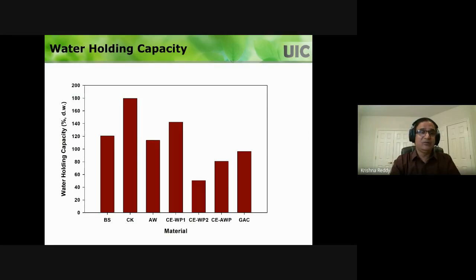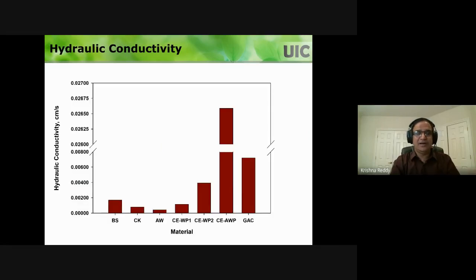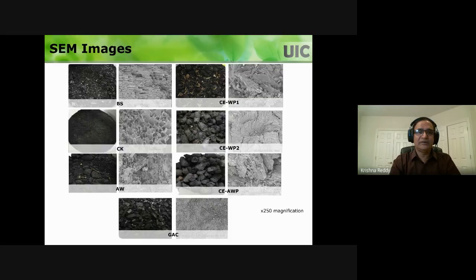Here, for water holding capacity, one of them has 180%, the other one has hardly 50%. For hydraulic conductivity, they are generally more like granular material, so they will have high permeability. No matter which biochar you're looking at, hydraulic conductivity is very high. You can do SEM images to look at their morphology and pore structure, and the beauty of these biochars is their internal porosity and porous structure that you can see in these images.